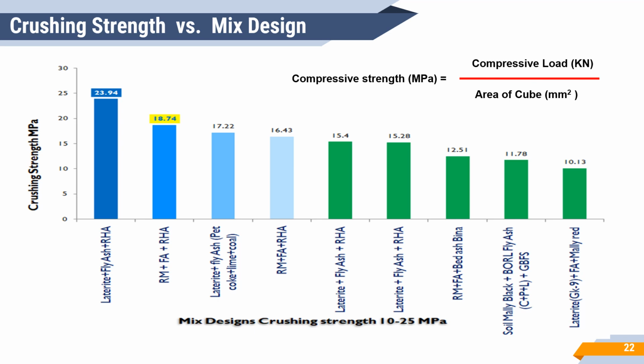Similarly, the required crushing strength for a specific combination matrix can be achieved by the selection of suitable material combination, or by changing the ratio of material input, or we can change the concentration of sodium hydroxide and sodium silicate in the activator medium. So the flexibility of choosing the concentration of alkali activator and the mix design as a whole makes this technique more preferable for making geopolymer matrix for building and construction application. Or the same matrix can be used for making low strength material for low load bearing application such as decoration purpose, wall tiles or partition walls, etc.